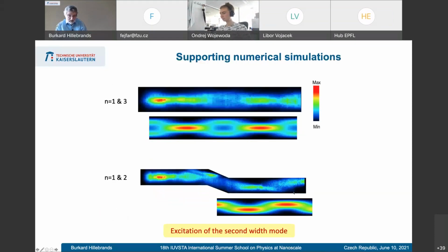So this all exists. Here you see again a comparison, and I find it rather convincing that you can identify here this mode superposition. Of course, you can do a full-blown program just analyzing the intensity, fitting the amplitudes of the different modes. Also, the phases are very important. I did not discuss the phase here. And then you get it. You get even small details like an edge mode, a mode which is just located here to this discontinuity.